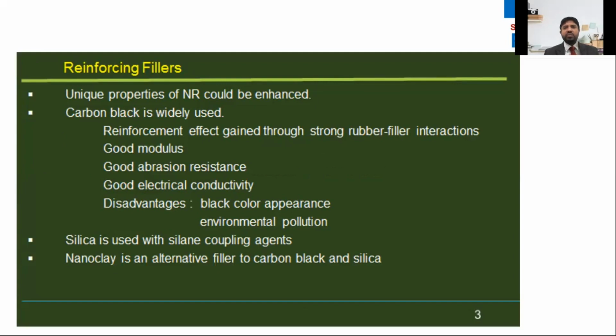With the support of reinforcing fillers, the properties of natural rubber can be enhanced further by adding a significant amount of filler. It is well known that tensile strength and modulus at 300% can be enhanced, but there is a significant reduction of elongation at break. If hardness is improved by adding fillers, there is a chance of reduction in tensile strength. However, I can tell you one thing: you can improve the overall mechanical properties with a smaller loading of nanoclay rather than a higher loading of conventional fillers. Anyway, proper handling of clay with minimum aggregation is a must to obtain superior results.